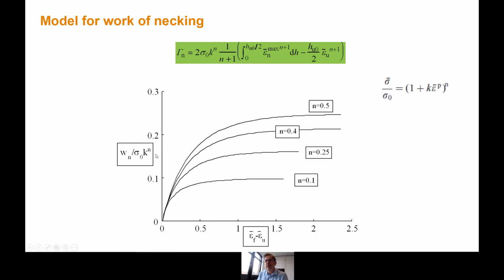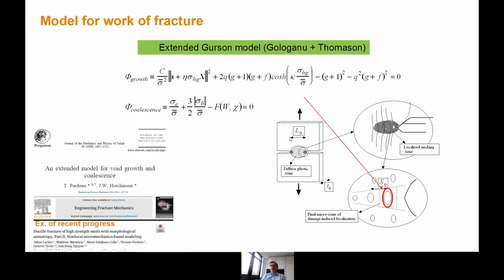So these are basically your three hardening parameters. And you see here the value as a function of the fracture strain minus the strain at necking. Before necking, there is no work of necking. It's zero. So it starts at the strain corresponding to the onset of necking, and you get an evolution which depends on the strain hardening exponent. Okay, that was for the work of necking.